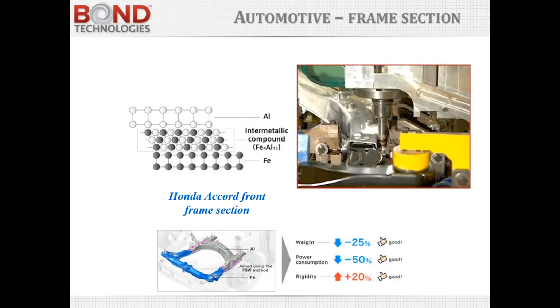from the standpoint of where the tool is positioned. So the pin tool is mostly on the aluminum side. But what happens is you do get these intermetallic compounds if the temperature is elevated too much. And these are fairly large molecules. They can be pretty brittle. So the way that Honda achieved success with this application, and the way others are achieving success with the joining of aluminum to steel, is to seek a colder region of the process window to keep the overall temperatures low and inhibit the formation of the intermetallic compounds.